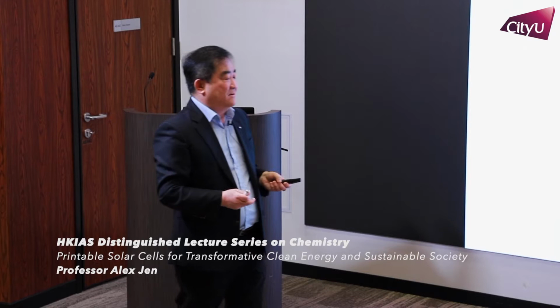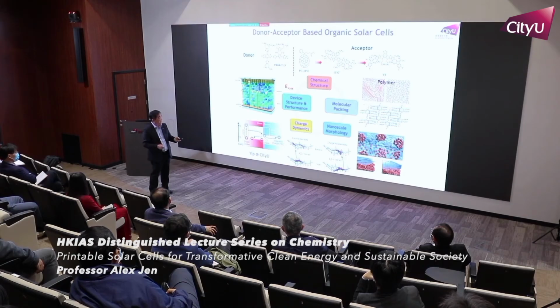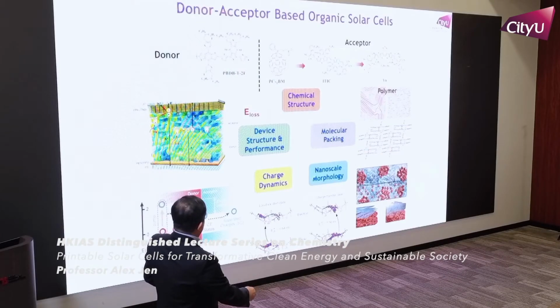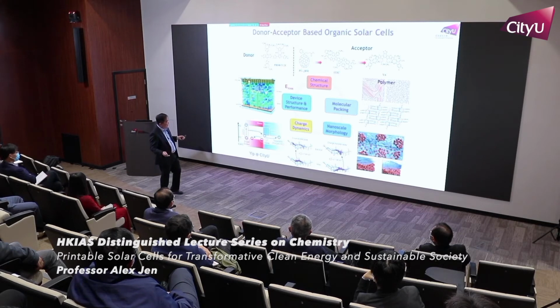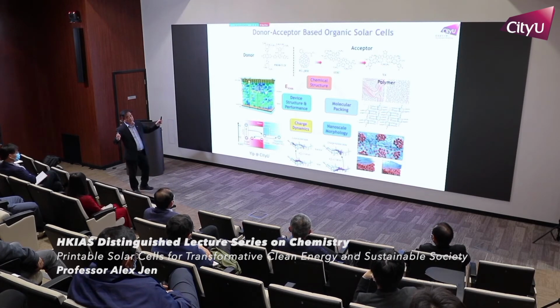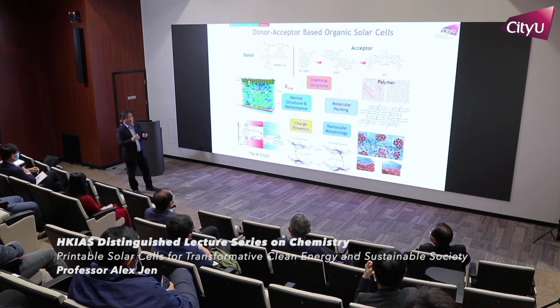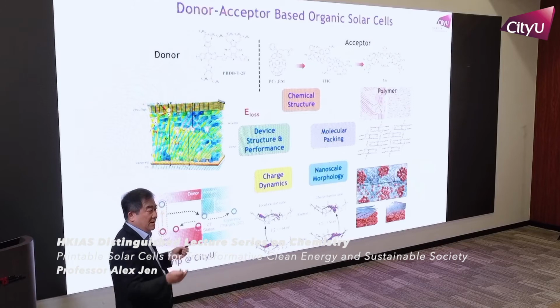By doing that, compared to perovskite, it's a little bit more complicated because now you have to control their molecular packing and also their morphology. Because if you look at this, this is an aggregate, where some acceptors aggregate together and pack very nicely. All this will have the path for the electron to transport to the cathode to be collected, and the hole will go down to the anode to be collected. So you need to find a way to control the packing, the morphology, the light absorption, and the energy of those donor and acceptor, so that when you mix them together they can have easy charge separation. All of that needs to be taken into account simultaneously in order to generate an efficient organic solar cell.